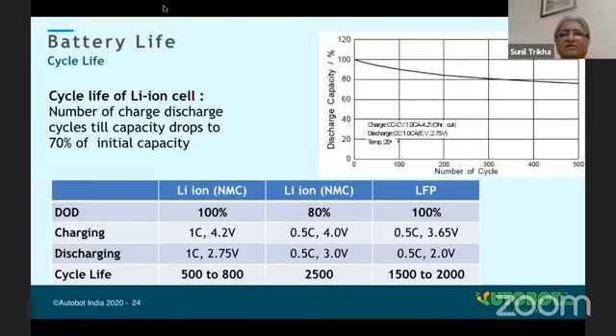The NMC battery, if you charge and discharge 100%, the life is between 500 to 800 cycles. But if you control state of charge, you don't fully charge, don't fully discharge, you can achieve even 2,500 cycles from the same cell. LFP cells, with full charging and discharging, have a better cycle life. You can get something like 1,500 to 2,000 cycles. This is for a comparison.